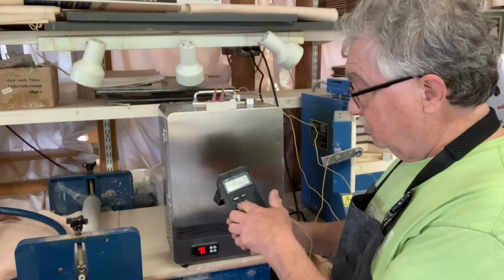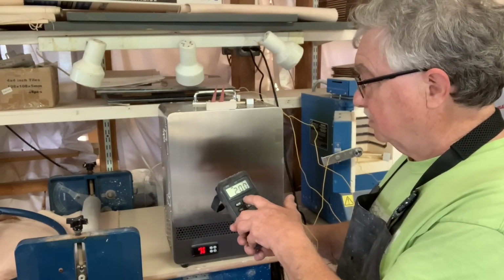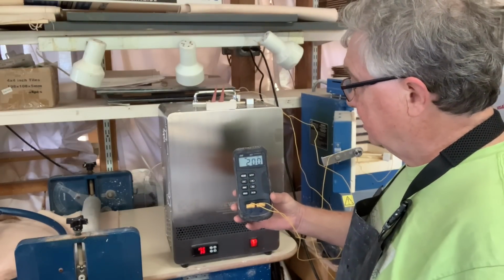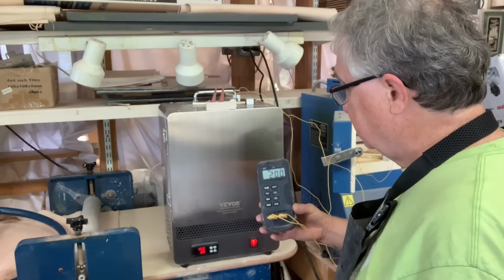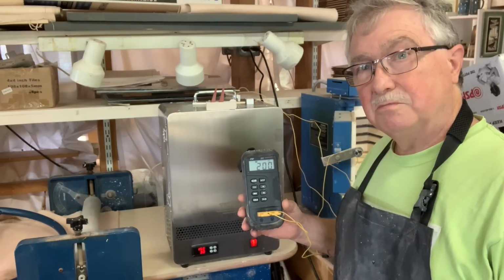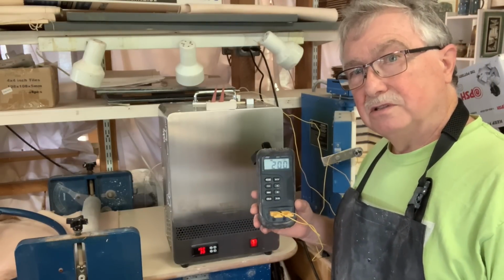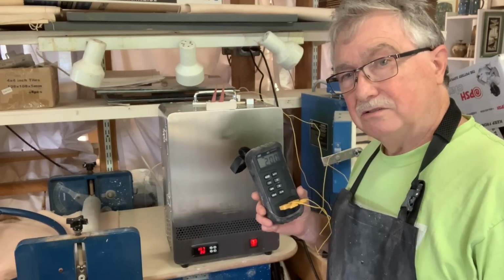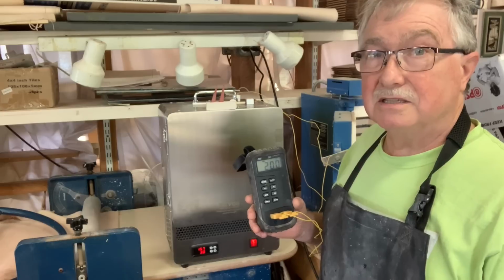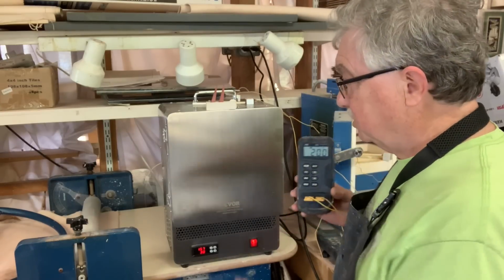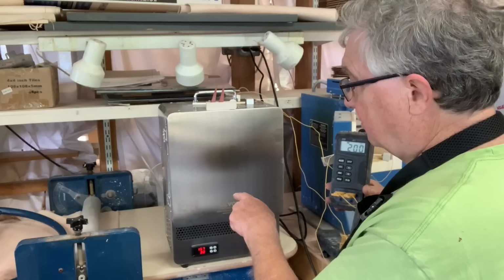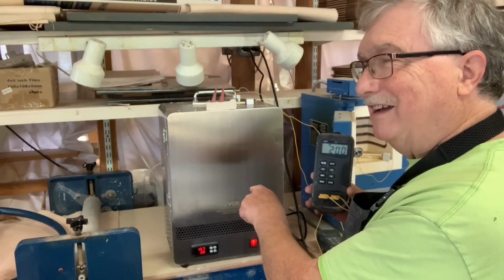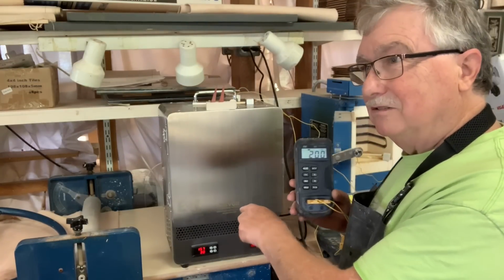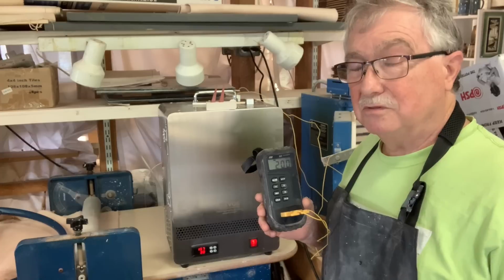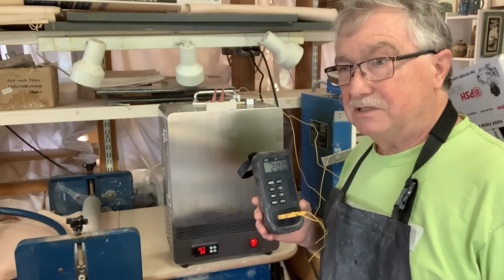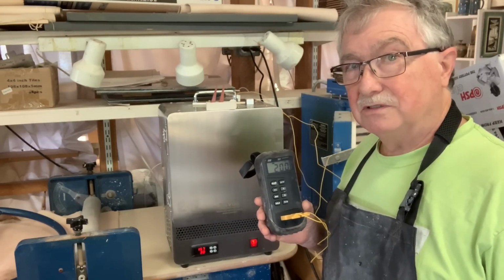So 42, what's the inside? Number one, it's reading 200 degrees centigrade, and this is reading 158. So there's still 42 degrees difference between the pyrometer that was in the kiln and this device here, which I think is pretty accurate. I've got two of them and they're both reading the same. So the pyrometer thermocouple inside the kiln is not as accurate, I don't think, because now it's down fairly low and there's still a big difference in temperature.